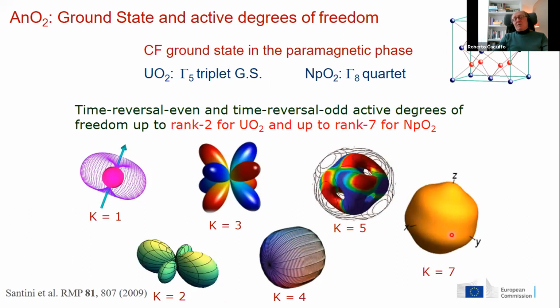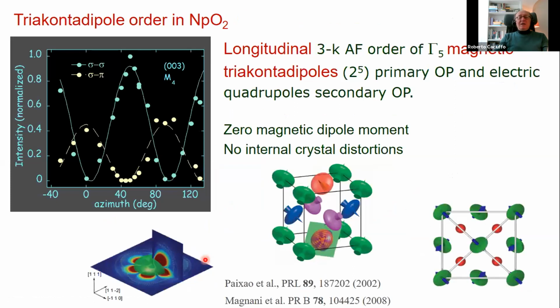Well, in the case of UO2, neutron diffraction revealed many years ago that the primary order parameter are magnetic dipoles. Resonant X-ray diffraction showed that electric quadrupoles order according to the same motif as secondary order parameter. On the other hand, in the case of neptunium dioxide, neutron diffraction and other techniques failed to identify the primary order parameter. Instead, by